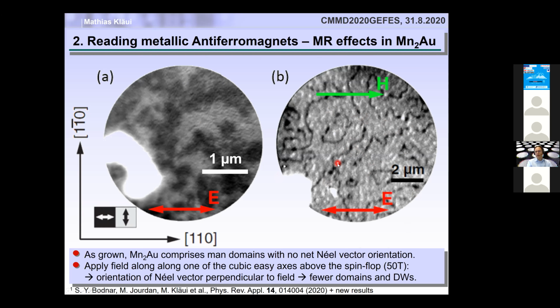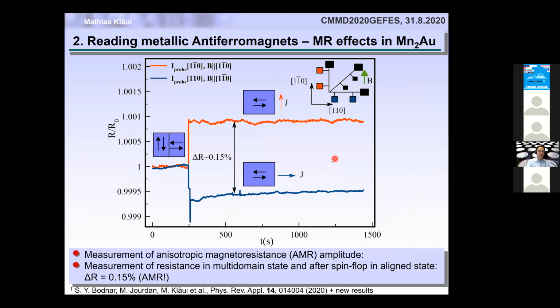So if you have a metallic antiferromagnet, let's see if we can also do AMR. And if we do that, it turns out that indeed we can get AMR. And the AMR in this case is about 0.15%. AMR meaning whether the current is flowing parallel to the Néel vector or perpendicular to the Néel vector gives us a different resistance level. So this 0.15% is not a huge AMR effect, but it's sizable, similar to what one can get in ferromagnets.